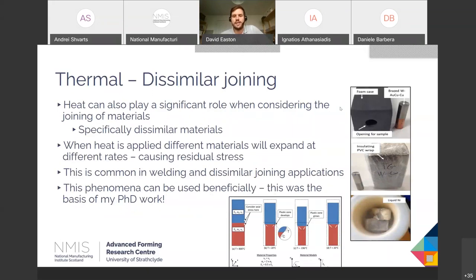A quite specific aspect of the thermal side is moving away from heat as an option to cold as an option. And this is quite personal to me. This was some of the work I did earlier in my career. In dissimilar joints, we have a problem of high stresses developing. As parts expand and contract, stresses develop at the interface, and that's just a reality of dissimilar joints. So what we can do to overcome this is to use temperature in a different way. We cool things down so they're very cold, and we basically reverse the typical expansion and contraction relationship that we see. This can relieve stresses, and it can give us more beneficial residual stress states.